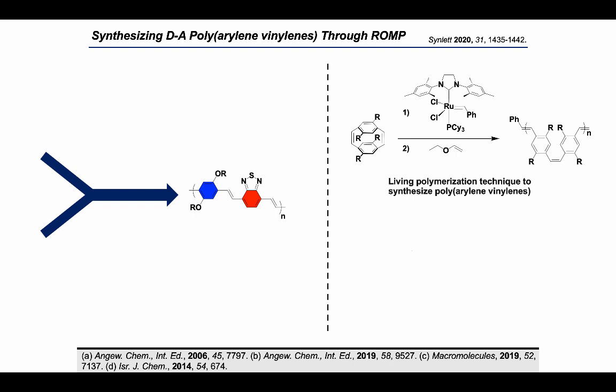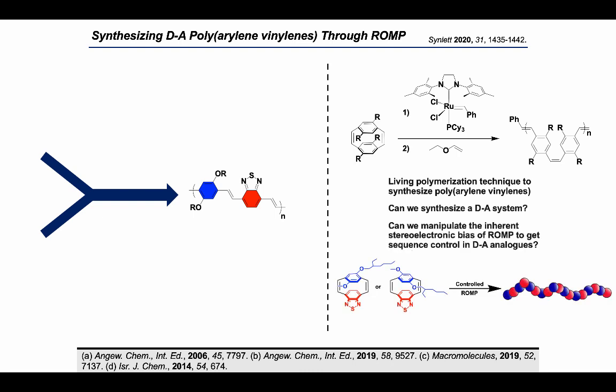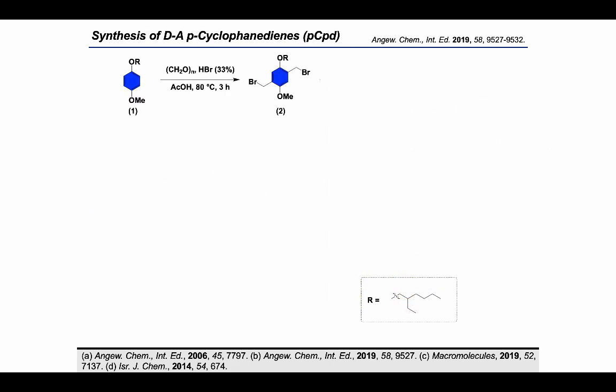Using ROMP as the platform, we asked, can we synthesize a PCPD, or paracyclophane diene, comprised of an electron-rich and an electron-deficient aromatic ring to synthesize donor-acceptor PPVs with controlled molecular weights and molecular weight distributions? To achieve this, we followed some known protocols, making modifications where necessary owing to the differing reactivity of our acceptor unit.